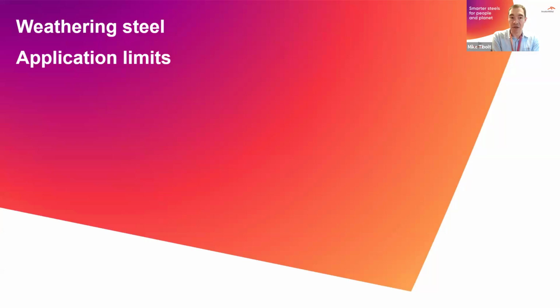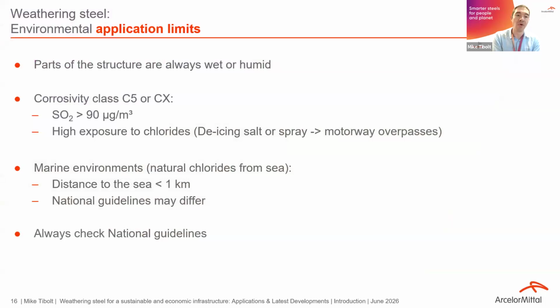Of course, there are some application limits because, as I said at the beginning, the patina should form well, and therefore you have to respect some conditions and application limits. You should not apply weathering steel for parts which are always wet or humid, for instance, which are always in the water or which accumulate water, because then the patina will not form. Also for corrosivity class C5 or CX, which has a sulfur dioxide concentration of above 90 microgram per cubic meter, you should not use it.